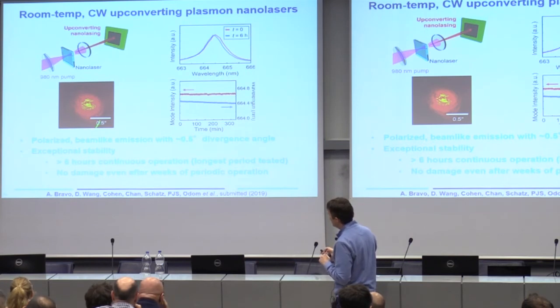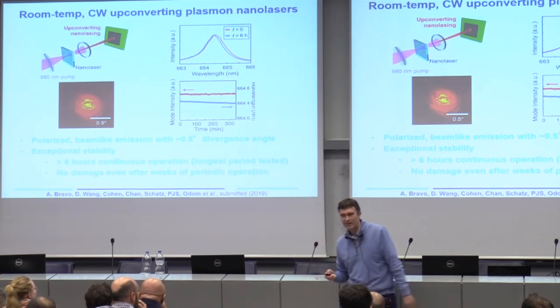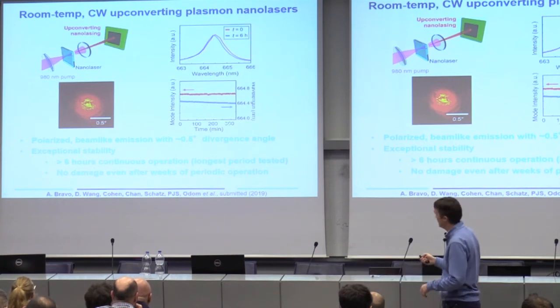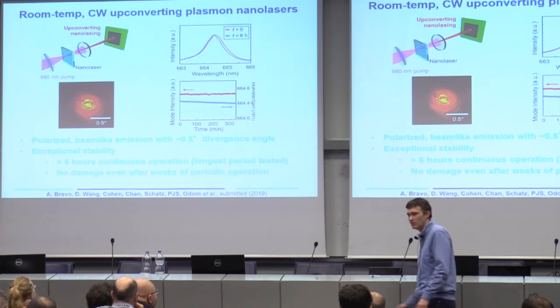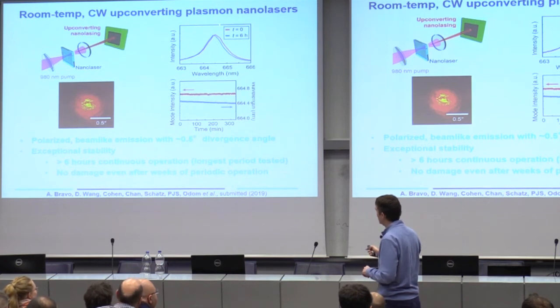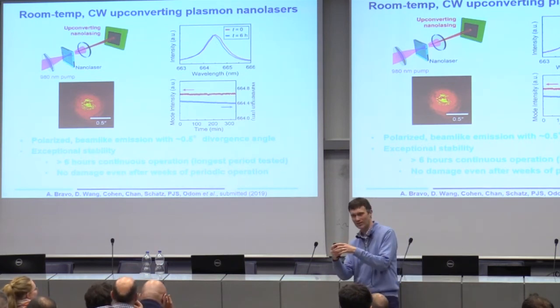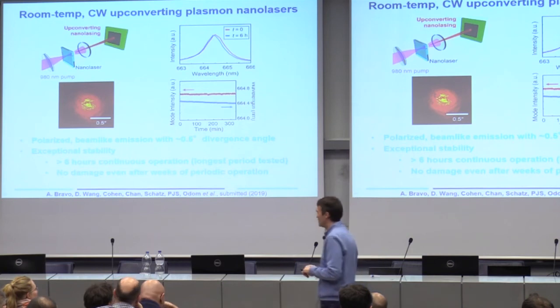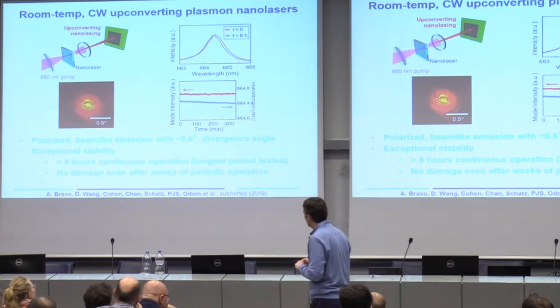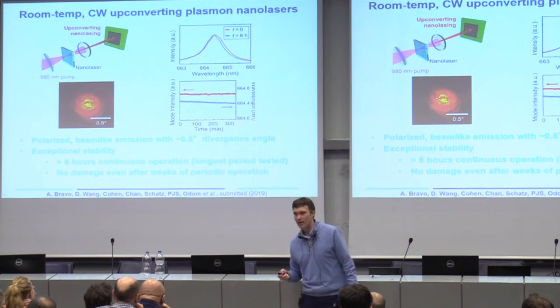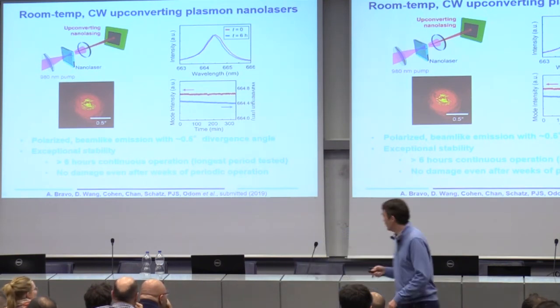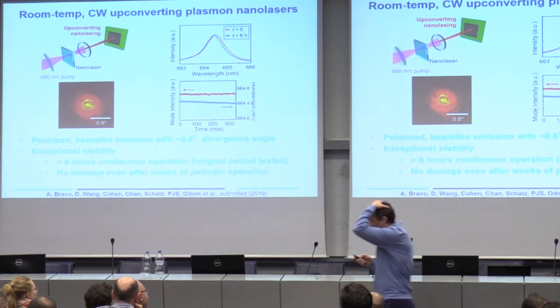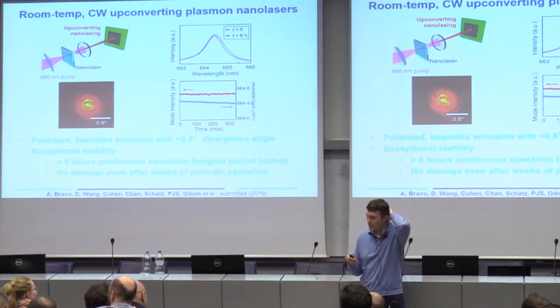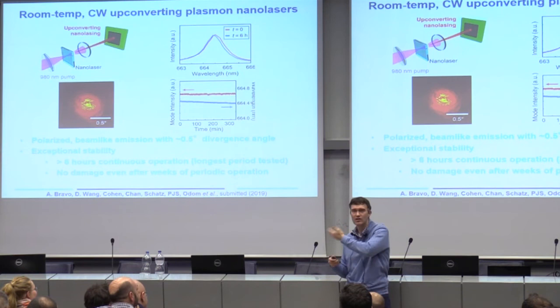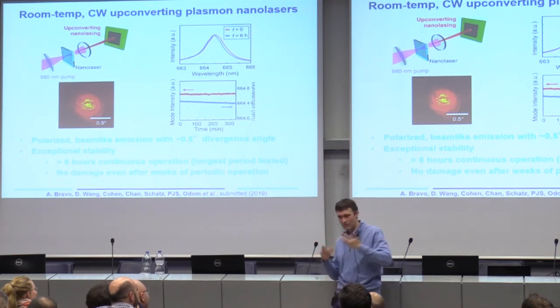We characterized our beam. It does come out as a beam with about a 0.5 degree divergence in these materials. And again, they're super stable. For as long as we are pumping them, they keep working. We get a little bit of drift. I assume that the plasmonic nanoparticles are annealing as we go, but they keep lasing, which is great. No damage even after weeks of periodic operation, which is pretty cool. This is something that we've submitted now, and I think it offers a route to easily creating on-chip type lasers that could be useful for communications, maybe biosensing.